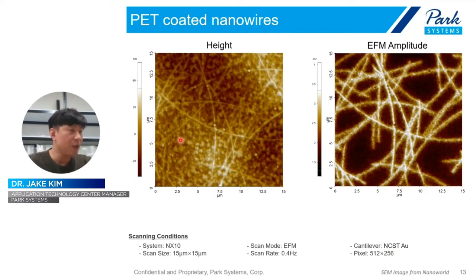And this is quite a good example of EFM measurement. Based on the PET substrate, there are nanowires in here. From the height image, okay, we can see some nanowires in here, but cannot see some clear one. But in the EFM image, the EFM signal, we can clearly see the difference and clearly see the contrast between the PET substrate and nanowire.